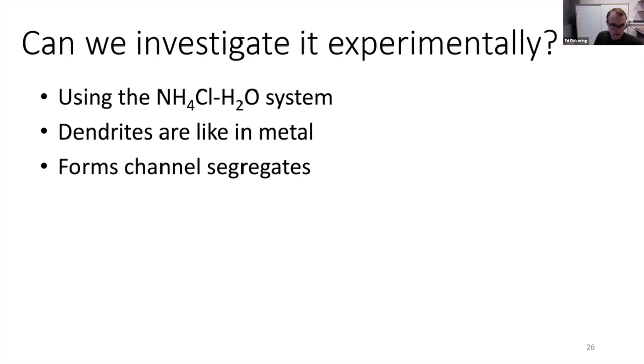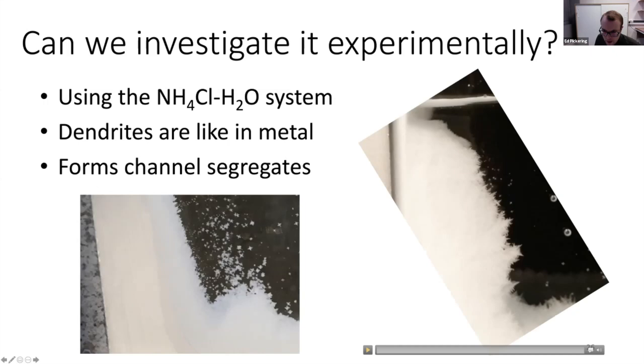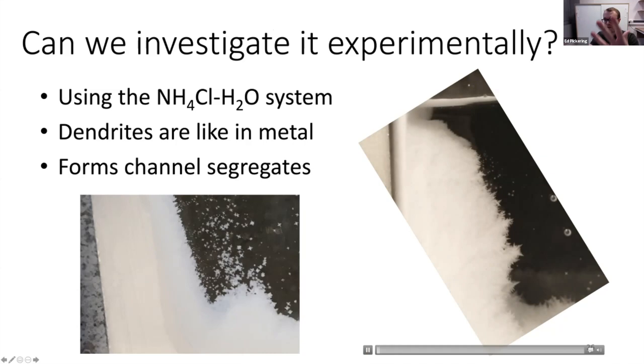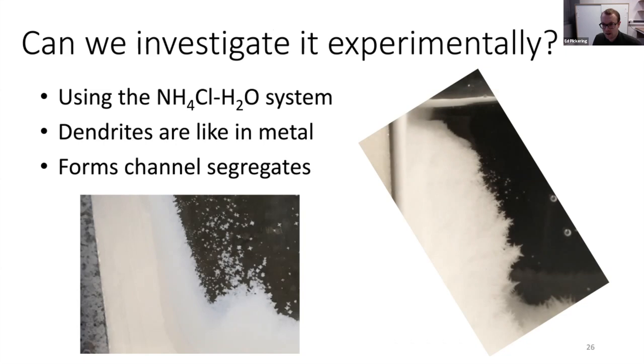And I think in this, yeah, I've got a video here. So in this particular case, the ammonium chloride is forming the solid, and it's rejecting water into the solution of ammonium chloride and water. And that is in fact floating. And when that happens, it forms channels. And I think you can almost see some of the channels here. And at the same time, the fluid flow through these channels rips out dendrites and throws them into the bulk liquid. So you can see this crystal rain that I was talking about earlier. In real time, you can see it happening.